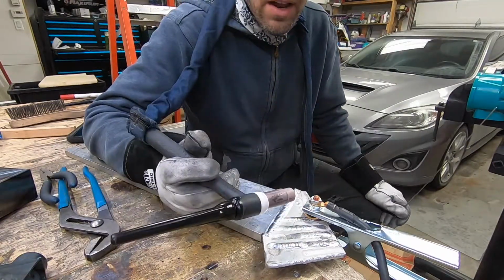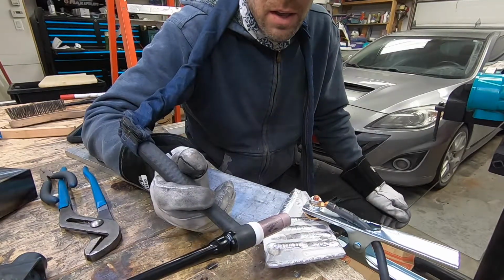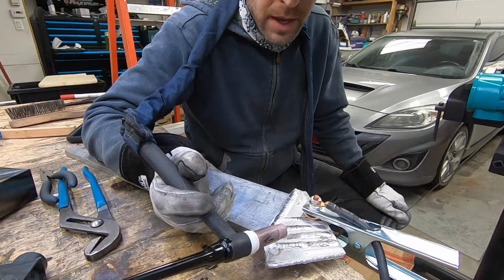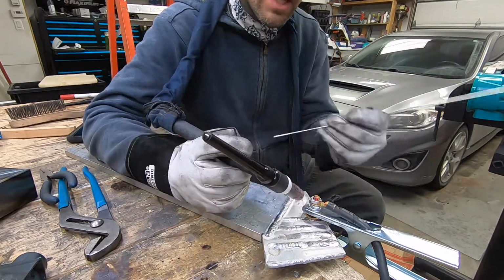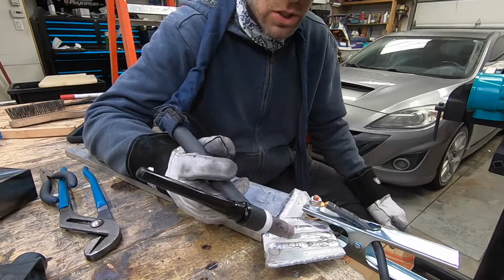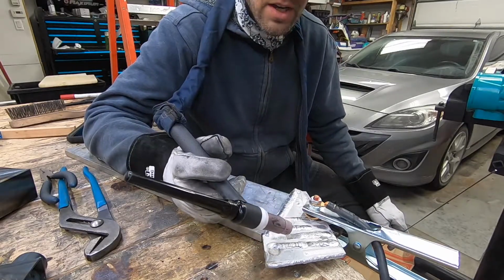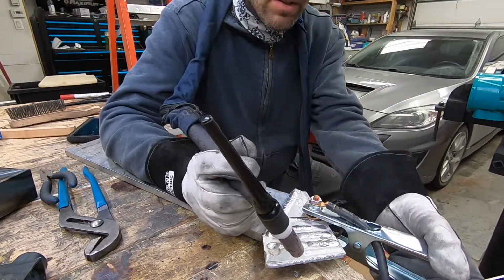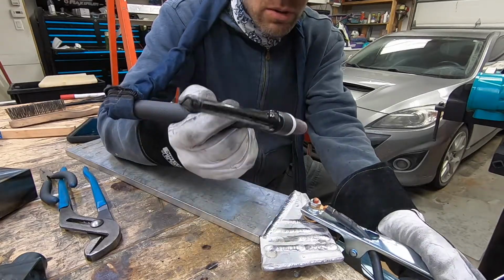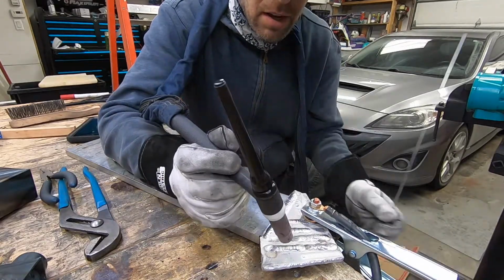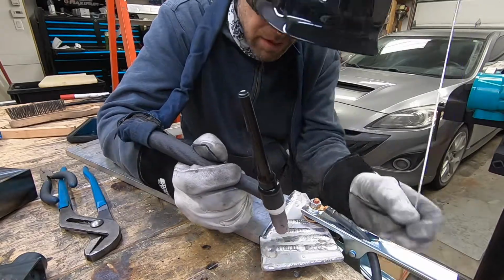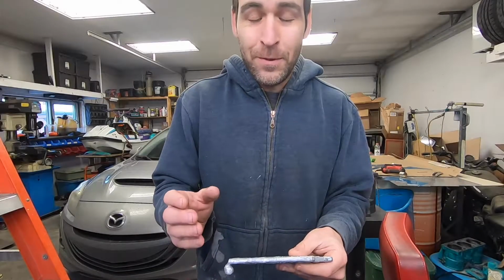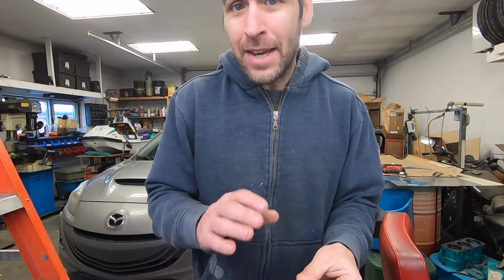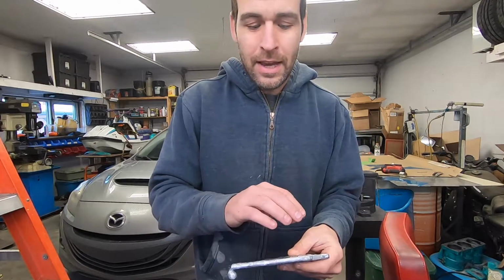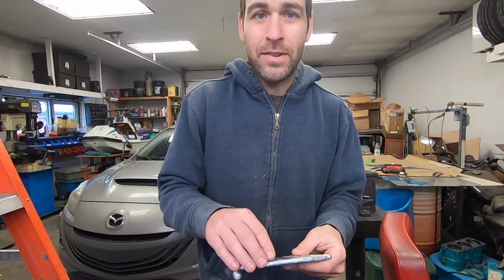The arc would not follow. Yeah, the arc was constantly coming off the back side of the torch. I could not get the arc to stay underneath the tungsten. That usually indicates a contaminated tungsten from what I understand, but alright, it's a few days later and I think I have an explanation for the arc jumping off one side of the electrode.